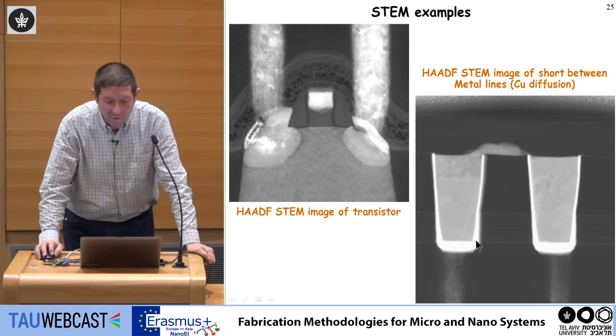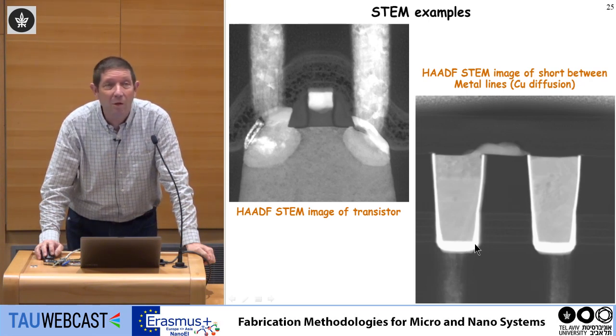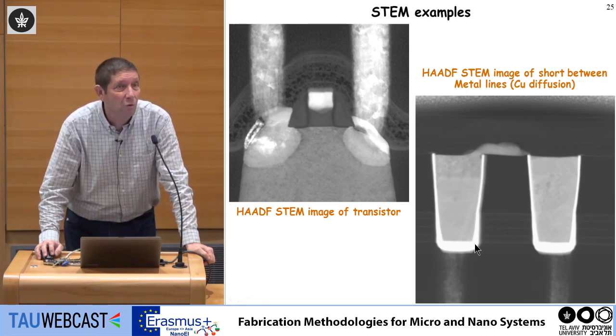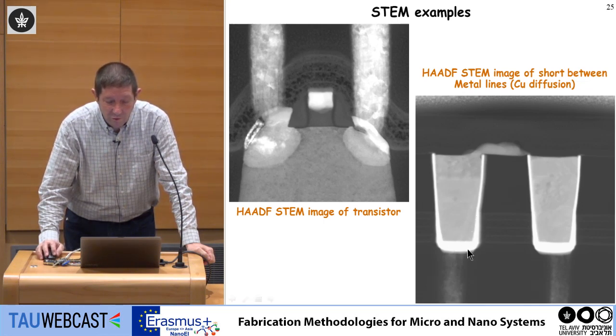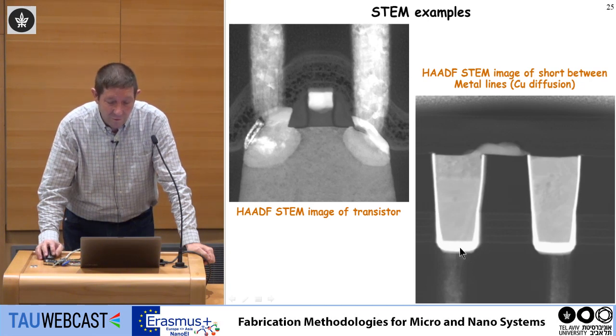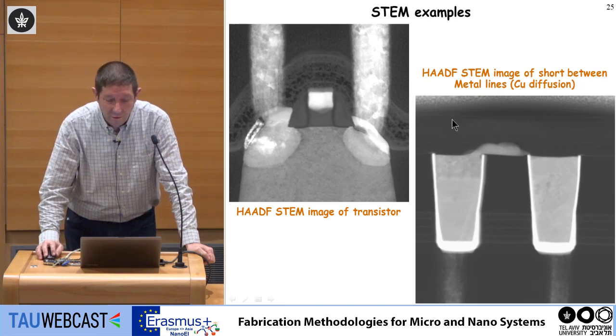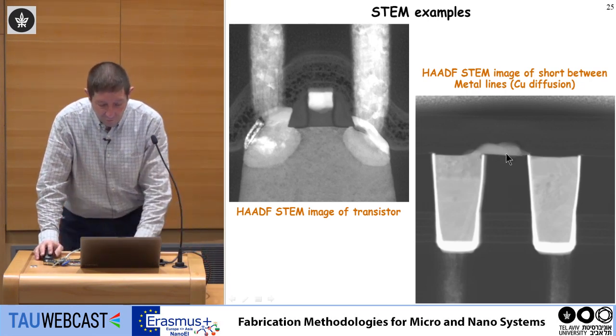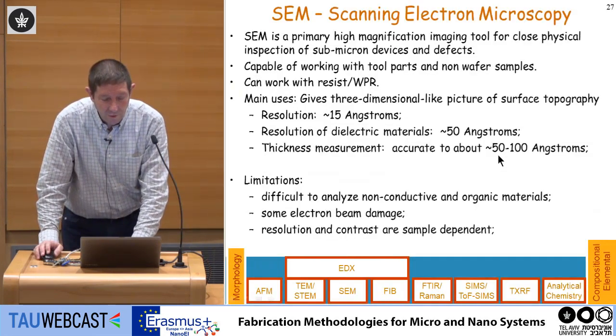And why is the barrier lighter than the copper? Because this is tantalum nitride, and tantalum has a much higher atomic weight than the copper. So this looks lighter. And by the way, you can see here the step coverage. This was done probably by sputtering, so it's thick here on the side walls. It's thinner because the atoms during deposition came from the top. And this is a nice short, probably by copper diffusion from here to here on the surface under, this is the insulator, so this is a metal failure. So this is the STEM summary, and I think we'll take